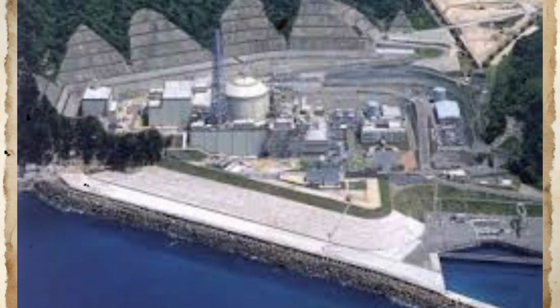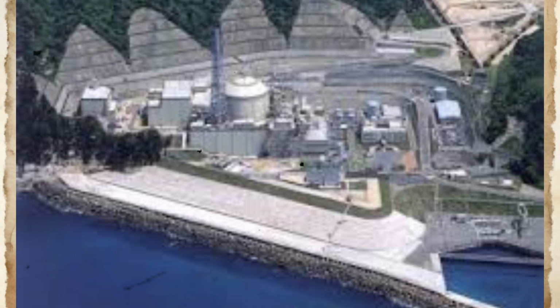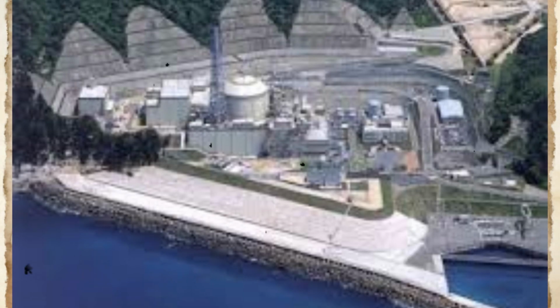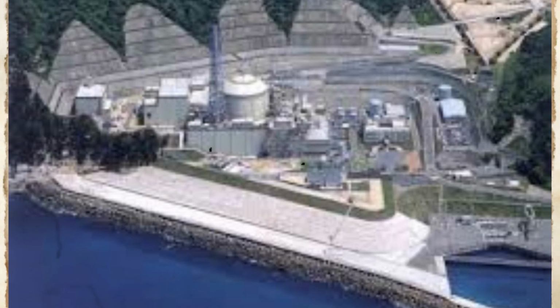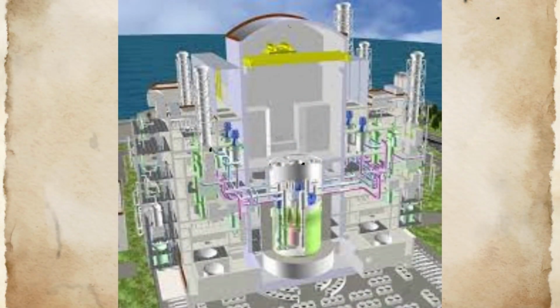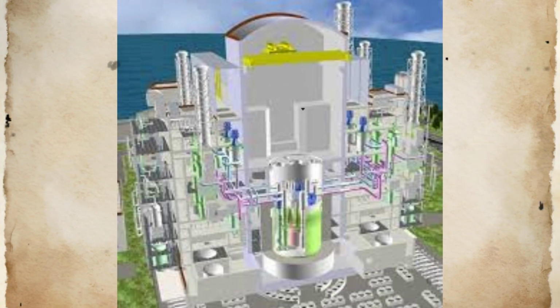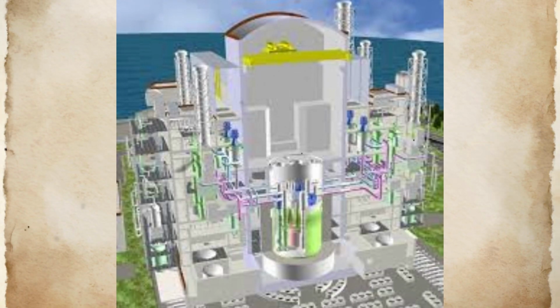failure. The failed thermocouple well tip was eventually located using a CCD camera inserted into the sodium inlet header of the superheater, where it was found in the distributor at the top of the superheater. The discovery location confirmed that the separated tip had been transported through the secondary loop piping by sodium flow, eventually coming to rest in a region where flow velocity decreased sufficiently for the component to settle.